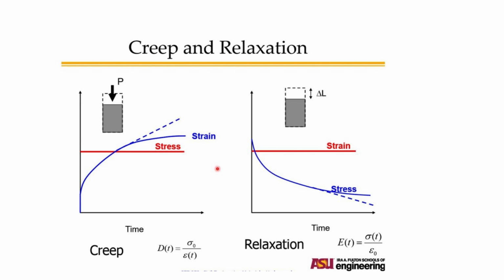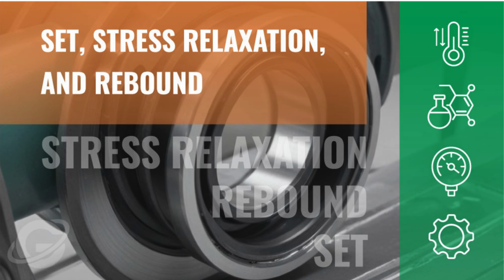The creep and stress relaxation properties of a polymer can be described by the time-dependent moduli E_C and E_R. The creep modulus is the ratio of an imposed constant stress to the time-dependent strain, while the stress relaxation modulus is the ratio of the time-dependent stress to an imposed constant strain. Practical examples of the need to design for stress relaxation are in seals where the sealing force must remain adequate under conditions of constant deformation, or when a metal peg needs to be held in a plastic block by push-fitting into an undersized hole.